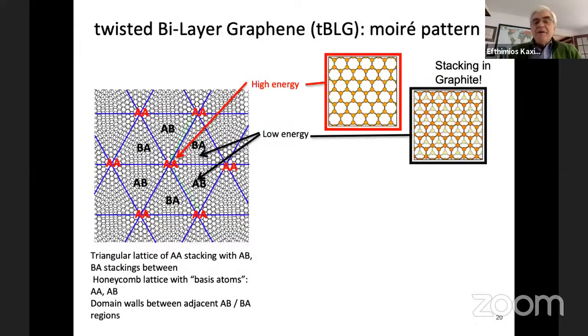Okay. Now, what happens in twisted bilayer graphene? You take two layers, you put them on top of each other, and you form these interesting patterns that I showed you earlier. And in some regions, you have this kind of arrangement. One layer, the top layer shown in orange, is exactly on top of the bottom layer. So you don't even see the bottom layer. So these are regions that are called AA. The A lattice is on top of the A lattice, and the B lattice, of course, on top of the B lattice. So you don't see the second layer.